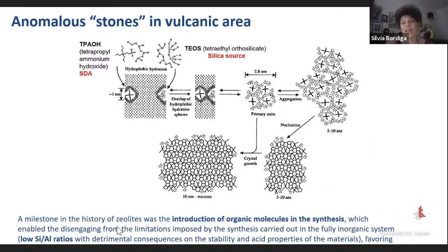And the big change in this field came when the use of templating was introduced in order to enlarge the possibility of structures and also of composition, because zeolites with a high aluminum content very often don't need a structural directing agent, but when we want to prepare materials with a lower aluminum content, instead, very often we need this extra element, which guides the building of the three-dimensional network.